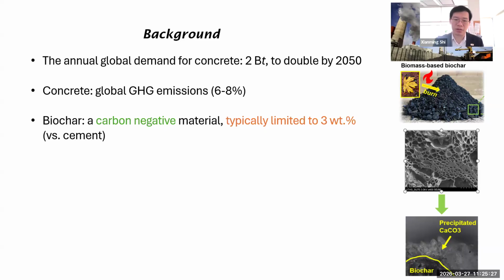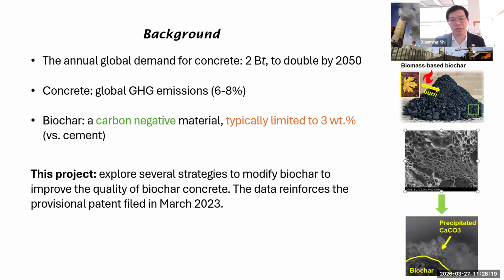Of course, alternatively, what naturally happens is the biomass would either catch fire or go through fermentation and release CO2 or soot or methane. Those things are very powerful. Actually, methane and soot are more powerful than CO2 when it comes to global warming potential. The challenge, though, is traditional wisdom, again, because of that loss on ignition or incompatibility with concrete admixtures. Typically, people are playing with 1 to 3% by weight of cement when it comes to exploring the use of biochar in concrete. That was kind of an unwritten, unstated assumption. And then in 2023-ish, we decided to challenge that conventional wisdom. So this project aimed to explore different ways to modify biochar to improve its quality or compatibility with concrete.